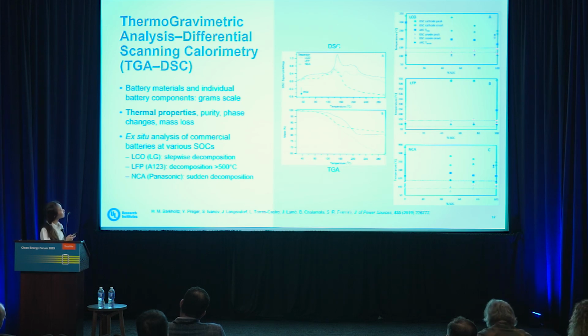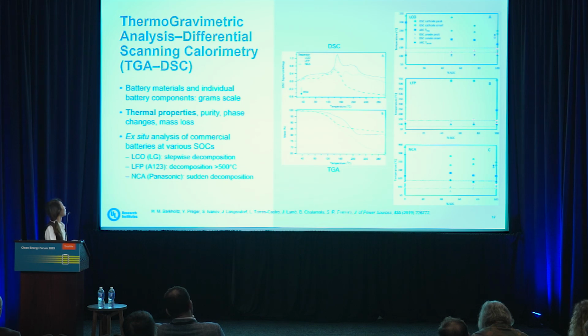On the right here, the DSC that's paired with TGA was performed on the separators. You can see that the separator decomposes above 100 degrees Celsius, and there is mass loss that comes with that decomposition. For the authors, this is the summary of the findings. They found that for LCO, there is a stepwise decomposition, whereas NCA has a very sudden decomposition when you heat the sample. And LFP is the most stable because of the cathode, and the decomposition occurs above 500 degrees Celsius. So this is on the smaller scale. We can also find out thermal properties on the larger scale as well.